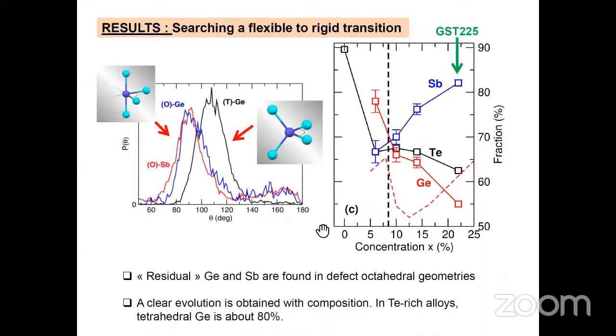We first see that again, in GST 2-2-5, we have two populations, a population of tetrahedral Ge, whose fraction we just found in the previous slides, and a defect germanium, which has essentially the same features as the one you are expecting for antimony, which is dominantly fourfold with 2 vacancies.